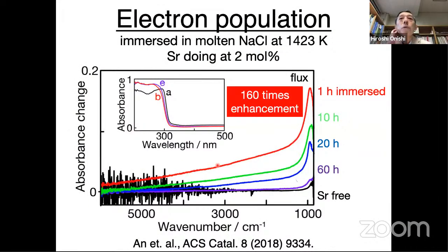So here we compared how to prepare our photocatalyst by changing the time for heating. This type of photocatalyst is very simply made. Make a mixture of starting materials, strontium, sodium, and tantalum. Then make a mixture in a crucible and heat it up in a furnace in air, say around 1000 degrees C.